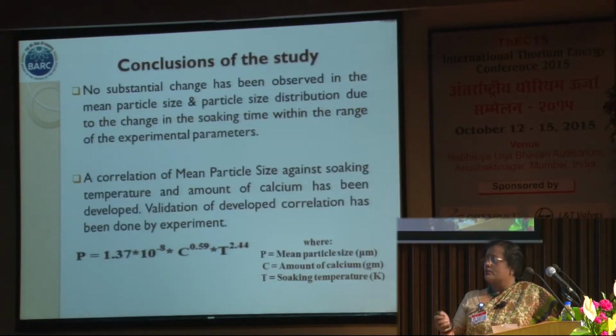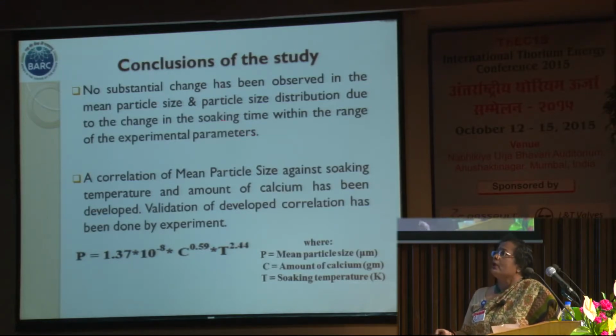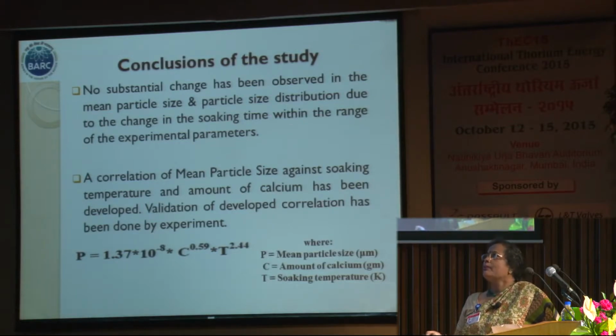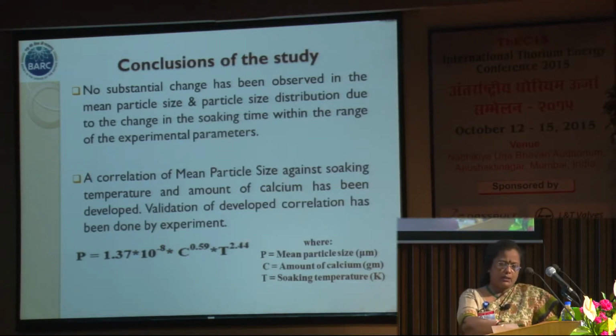Here we only wanted to show that there was not much effect on the mean particle size and the particle size distribution due to the change in soaking time within the range of our experimental parameters. However, with the soaking temperature and amount of calcium within the range of our experiment, we could see there was some effect, and based on this, we have developed one relation so that we can utilize it for our production.